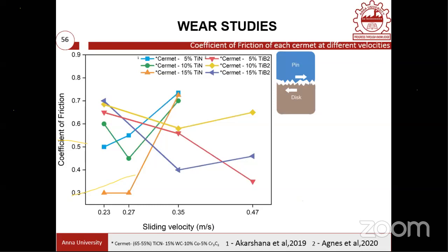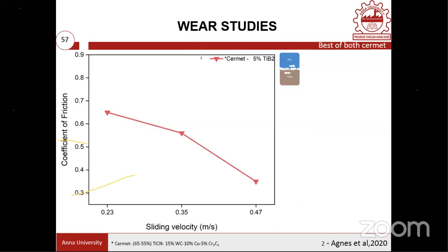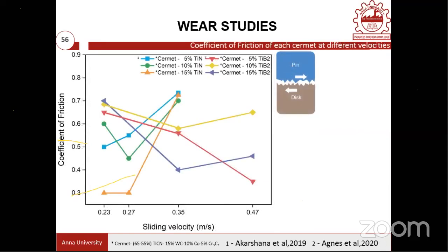And one more benefit is the coefficient of friction. The coefficient of friction keeps on decreasing with respect to high speed. When the coefficient of friction is reduced, the frictional forces will be reduced, and proportionately the heat generated because of the friction will also be reduced. As a result, the chip tool interfacial heat will be reduced. That means the tool life will be improved, and it also has an effect on cutting forces. As a result, you have to have a minimum coefficient of friction. So at high speed cutting conditions, the coefficient of friction is very, very low for the developed tool.